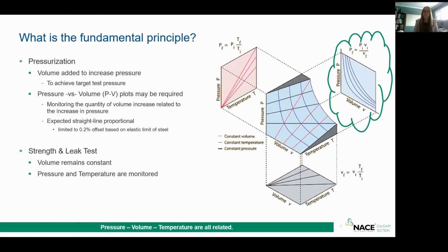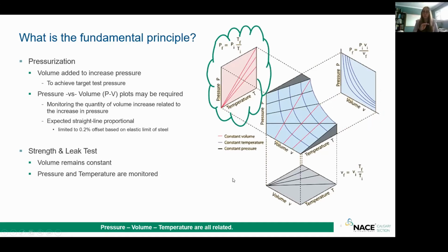A pressure volume plot monitors the correlation between how, when volume increases, pressure should also linearly increase. And so we measure it relative to a 0.2% offset, which is the elastic limit of steel, to ensure that we're not plastically deforming the pipe as we're pressurizing it up past its minimum yield strength, okay? In our strength and leak test component, the volume in the pipe remains constant, and we monitor pressure and temperature because this is a long-term hold. A strength test can be either 1 hour or 4 hours, and a leak test is always 4 hours in CSA pipelines. So these are the key topics to have in your mind.